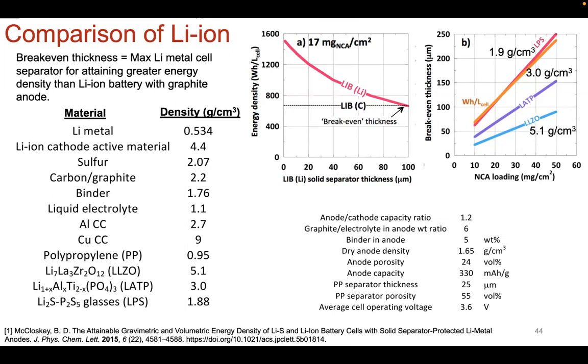So then the first question you have to ask is, how thick of a separator do I have to protect the lithium? The first order of business is to compare a lithium ion battery with a graphite, or C, anode as denoted here, to that of lithium metal. So if you assume 17 milligrams per centimeter squared loading of NCA, something state of the art, which in 2015 was a reasonable choice, and you say, if I don't have any separator thickness, I don't have a separator to protect the anode, of course my energy density is going to shoot up extremely high. Great. But then your cell's also going to fade extremely fast.